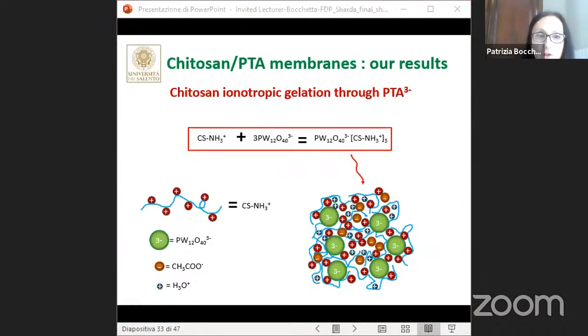Here, I have simplified the ionotropic gelation reaction. You can see that negatively charged phosphotungstate polyoxo anions are able to ionically cross-link the positively charged amine groups of chitosan. This occurs at the interface between alumina and chitosan solution. So a flat three-dimensional lattice of gel adherent to the alumina substrate is formed. The formation of ionic bonds is supported also by hydrogen bonds between the OH groups of chitosan. And so it is possible to create a reticular network of immobilized polymer, which can be peeled off from the alumina support.